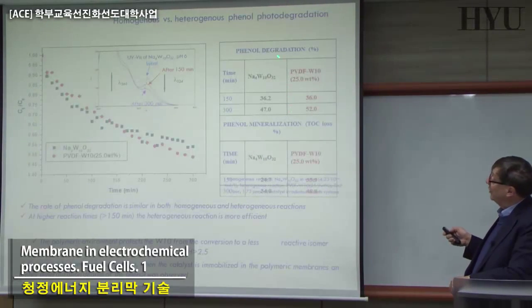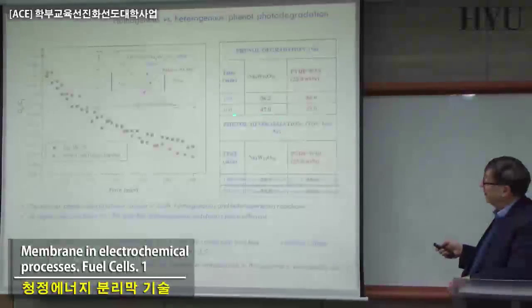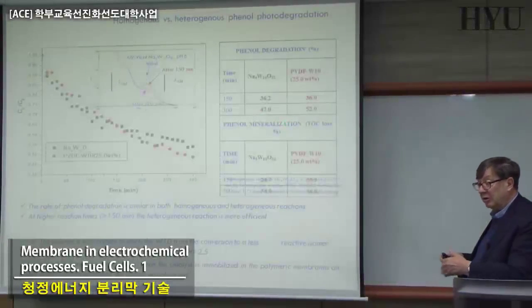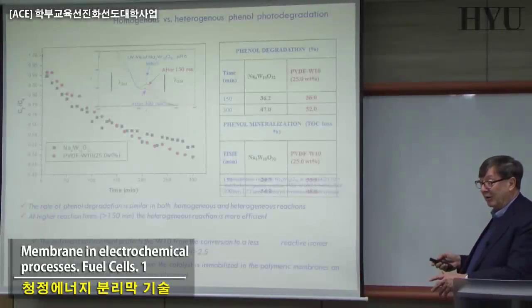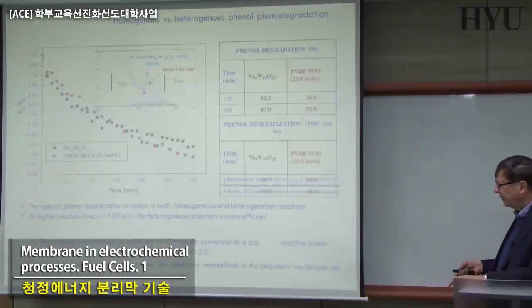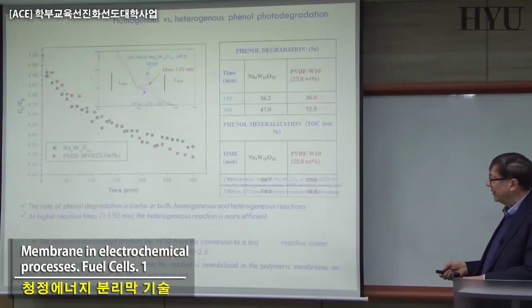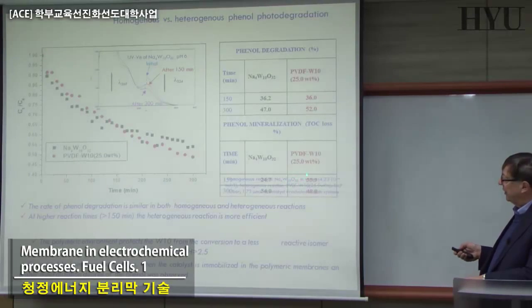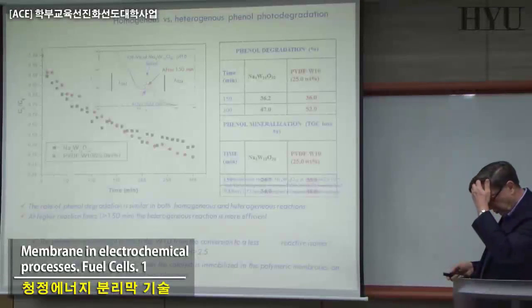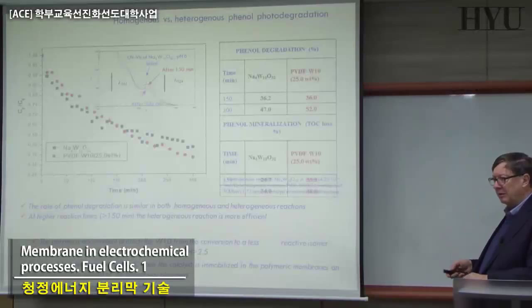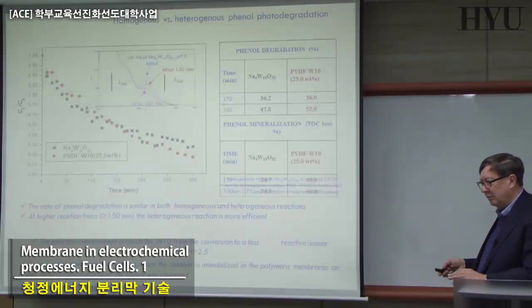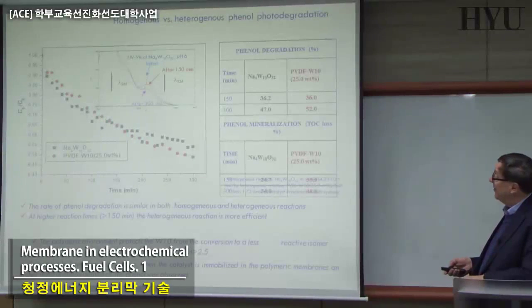And now you can try to study this phenol degradation and basically the phenol mineralization, that means the disappearing of the phenol in the system, and the result can be quite interesting. That is the case in which we have been using this polymer, this kind of catalyst. Now, if you want to change it, to improve the system and do something better, the situation is again more complicated than expected.